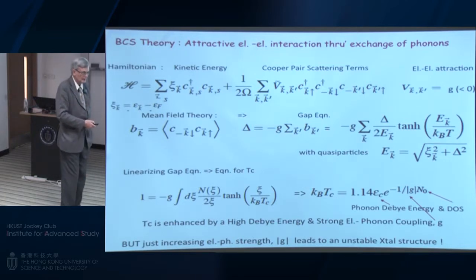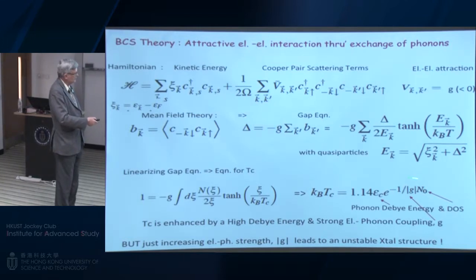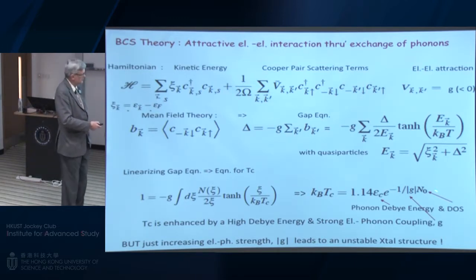But then you run into a problem: if you increase the electron-phonon coupling, that means the phonons couple more strongly to the electrons, and they can lower their energy, and before you know it, the phonons go soft. They go to negative energies, which means the crystal becomes unstable. So it's not so easy to just simply maximize Tc out of this formula, because it can lead you to a transition in the crystal structure, which in turn then lowers Tc.